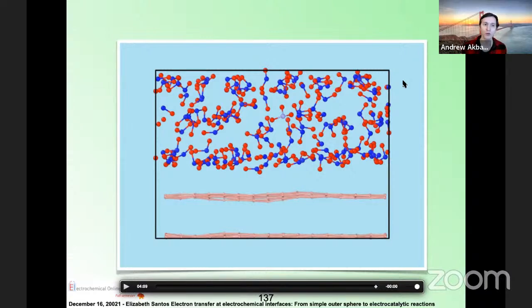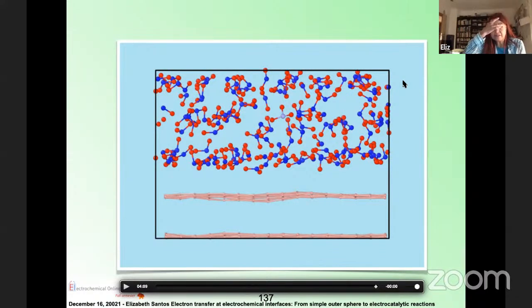For example, bigger or smaller, so you can make that functional different as a result. Yes, these are things that we have to improve. We assume that the interaction with the solvent depends linearly on the charge, through this solvent reorganization. But with the method, we use DFT with the usual functionals and so on. So we don't take that into account.